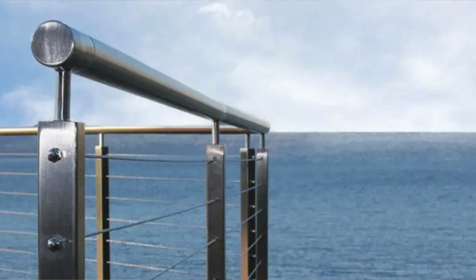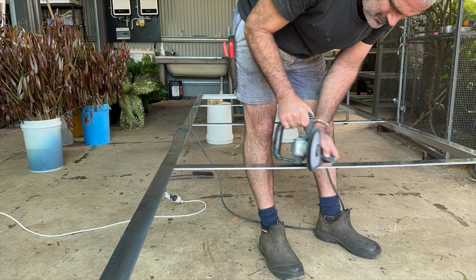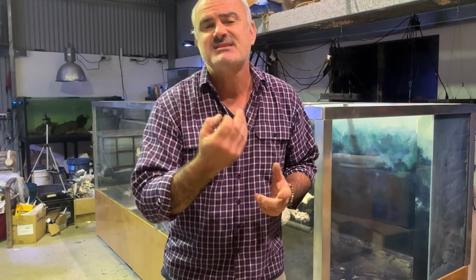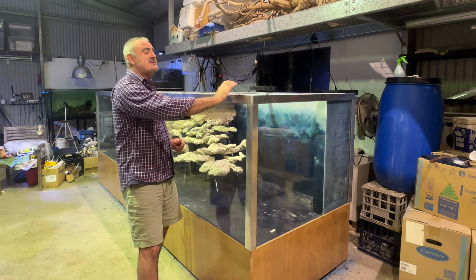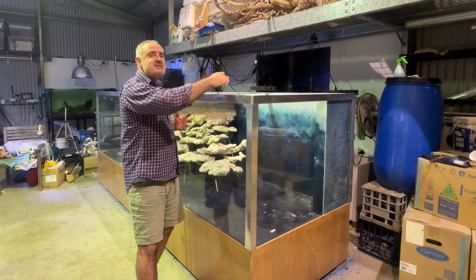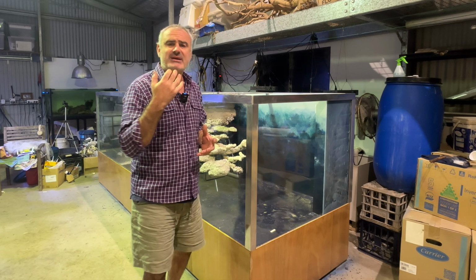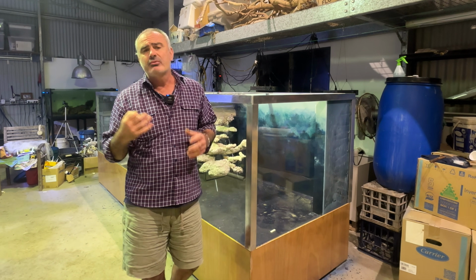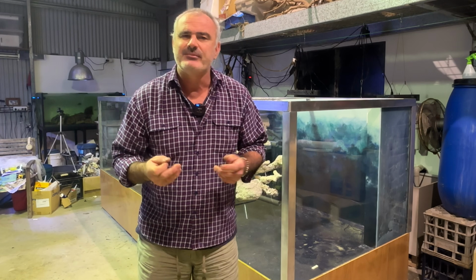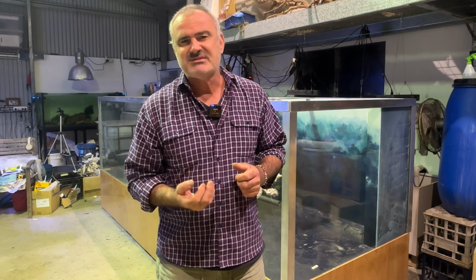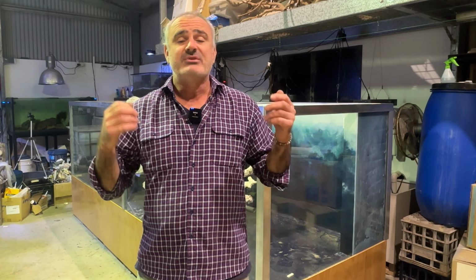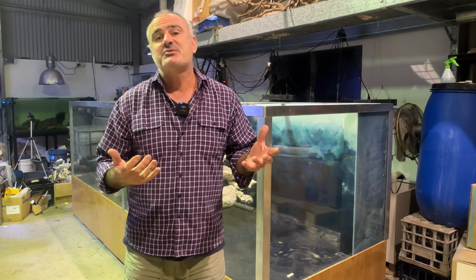And 316 stainless steel, of course, is what's considered marine grade stainless steel. And obviously getting as high a polish as possible would give it the most degree of resistance and weathering. However, if you've ever looked at highly polished stainless steel, particularly around the coast, you'll notice that it does tend to tea stain. And I was worried that if I did use stainless steel bracing, I would get the tea staining effect, which would potentially contaminate my saltwater coral reef tank with oxides like chromium and other nasty heavy metals. The other thing about stainless steel, of course, is that it's ridiculously expensive and it's a lot harder to actually grind and polish up.